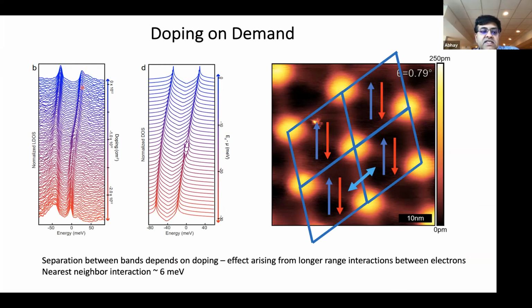What I want to show you from this data set is, again, how easy it is to dope this sample. All we do in this experiment is apply a gate voltage while performing our STM experiments. As you do this, you can see the chemical potential nicely shifting as a function of this gate voltage. And you can see that we can go precisely to 1/2 filling of this Moiré lattice, where you see a little insulating gap appear, exactly like transport had told us. Once again, this is just to say that it's really easy to cycle through samples by applying these gate voltages in these materials.